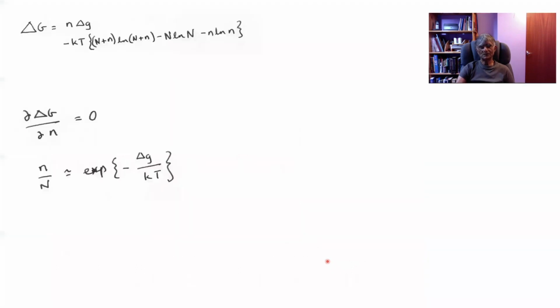Now, if we look at some basic thermodynamics of defects, then this term here, where we have small n, is the number of defects, and this is the cost of creating a defect, then this opposes the formation of a defect. On the other hand, when you take a perfect crystal and you introduce a defect, that increases the number of ways in which you can arrange the defect on the lattice, and therefore you increase the entropy, and this is the configurational entropy, and this term will favor the formation of a defect. So if you differentiate this equation with respect to the number of defects and set that to 0, then we get an equilibrium number of defects, and I emphasize the word equilibrium, at any temperature and in any material, right?